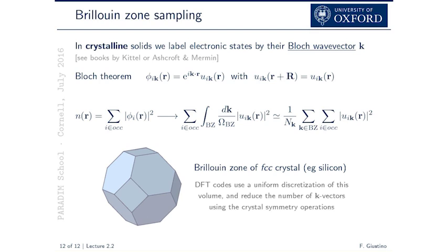So to give you an idea, this is the Brillouin zone of silicon. FCC crystal, you've seen this a million times. When you use this keyword and you set something like 4 4 4 0 0 0, that simply means take this and slice it with an array of 4 by 4 by 4 points.